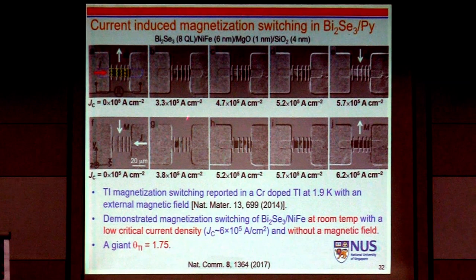So we chose 8 nanometers because this is kind of optimum, with a reasonably large spin efficiency. But always we have to think about device resistivity. If your device resistivity is so high, your power consumption will be so large. Then we put nickel iron 6 nanometers, and then we pattern into many different squares. So we want to show reliable switching. These yellow squares are each a single nickel iron square.